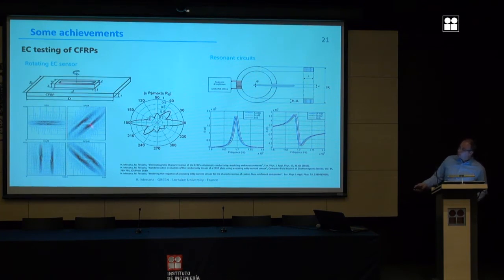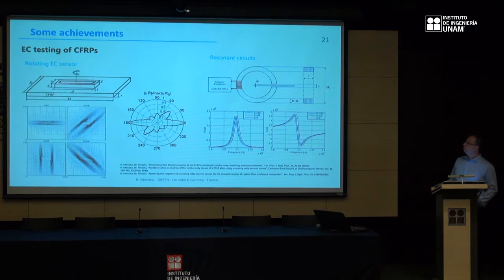And you have here the eddy current flowing in each ply of the multi-stack. We have also developed characterization methods of this type of material based on resonant circuits. We found that the resonant frequency is very sensitive to the variation of the conductivity, and here we have a single ply put in the gap of a resonant circuit formed by a ferrite core. It's a ferrite core that we cut in this direction, with a rectangular section. We wound a coil here on the ferrite. We connect it to an impedance analyzer.